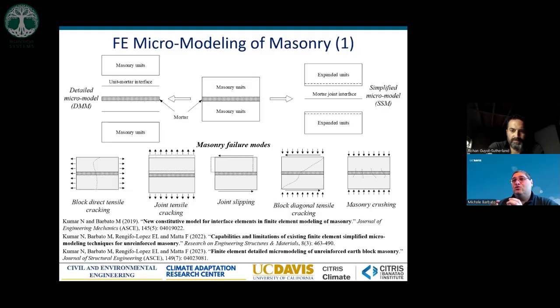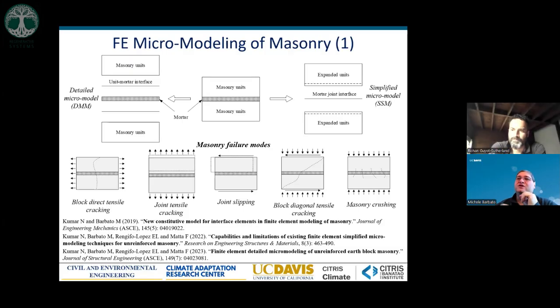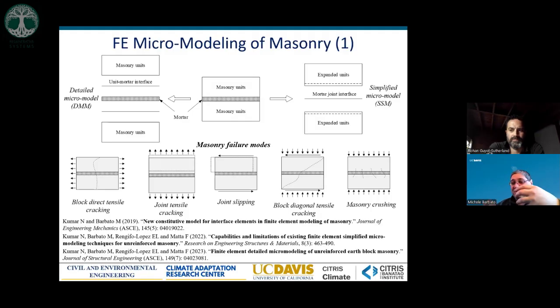What we need to obtain is a final model that is able to account for all of the different types of failures, which are going from tensile cracking of the blocks to tensile cracking of the joint, the slipping of different blocks one on top of the other, diagonal cracking, and then crushing of the masonry. So we need something that is able to identify all of these mechanisms of failure, because any of them could happen.